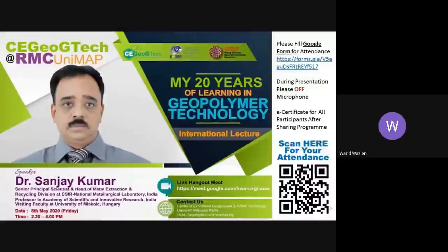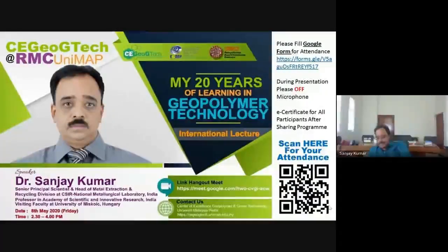See, red mud is a very difficult material because it is extremely fine in size, with a lot of iron oxide particles in it. But people are using red mud in geopolymer. In fact, we have a publication on it. We have also used red mud in the geopolymer. The problem is you cannot use more red mud. You cannot make a geopolymer from 100% red mud because of two reasons.